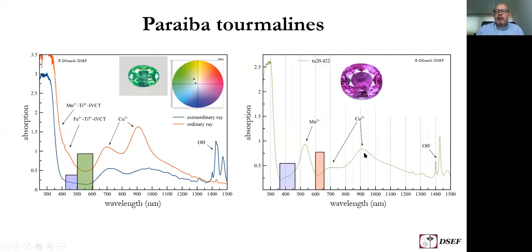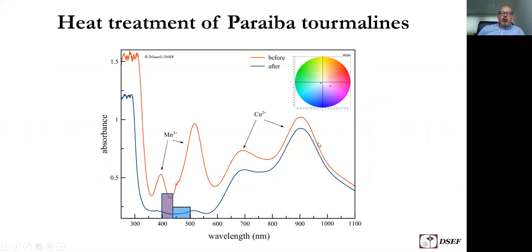Again, you see the 2 copper bands and you see a distinct absorption band of manganese 3+, with the absorption minimum in the blue-violet and in the red part of the spectrum, which produces the purple color. Now, what you can do with this type of stone is heat it to get rid of these manganese absorption bands. This is shown here, an unheated copper-bearing tourmaline of a purple color.